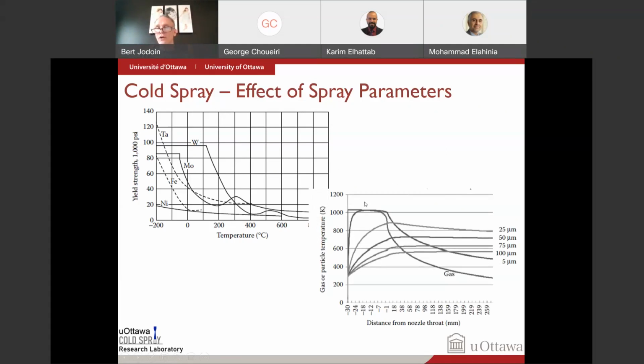You see the small particles, they go very fast, but they cool down much faster than the others because the gas here, if you look at the gas temperature drops because you convert thermal energy into kinetic energy. So the small particles, they drop in temperature very, very quickly. So they go fast, but they're cold. So actually the optimum is not to spray small particles because they go fast, but they're cold. So they don't deform that well. It's better to have larger particles that go a bit slower, but that are a bit warmer.